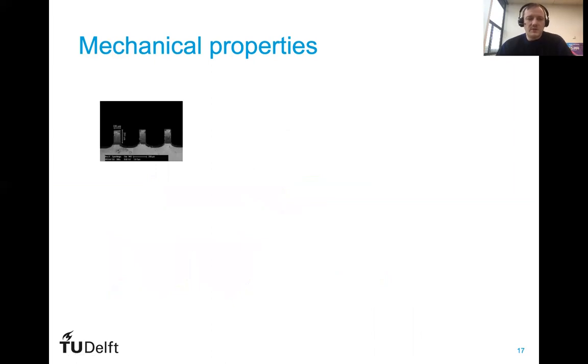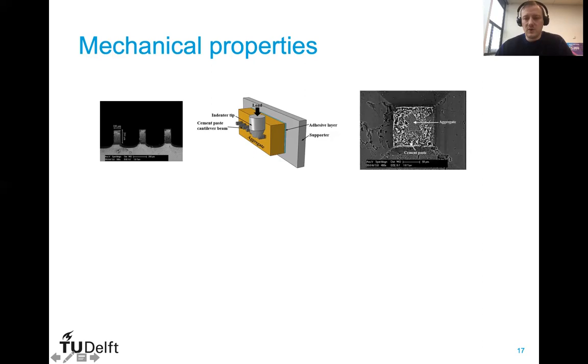However, apart from the matrix, we also have an ITZ in our cementitious matrix. So using a similar technique, we created microcantilevers that contain part of an aggregate in the bottom and part of the cement paste in the top. And then these microbeam specimens were loaded in flexure. And with that, we could measure first the strength of the interfacial transition zone. We can also observe the fracture surface, which also has some debris from the hydration products that have precipitated onto the cement paste.